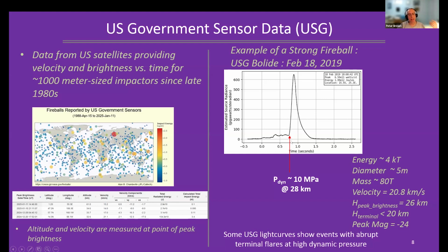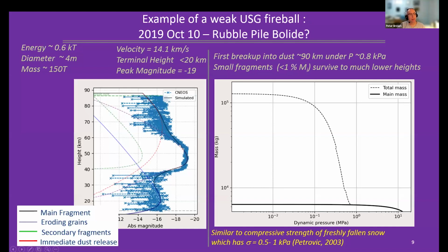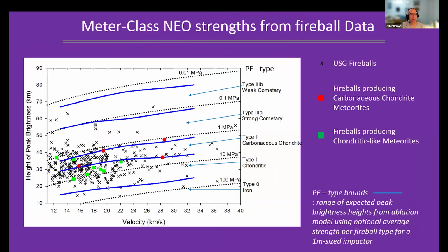So for instance, bodies that penetrate deeply come apart under high pressures, 10 megapascals pressure. Here's another example of a meter-sized object, actually about 4 meters in size, that completely broke up at very high altitude under almost no dynamic pressure. And then the grains and dust just rained down and ablate lower in the atmosphere. So this thing broke up under less than a kilopascal of pressure, and just shows that extreme range that we find in the strengths of these meter-sized objects.